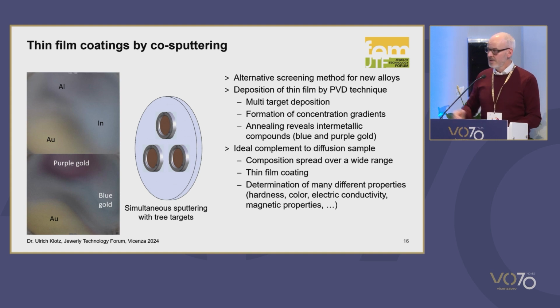So they are arranged in a triangle. And so they're sputtering material from different sides. So we get mixtures of alloying elements on this glass plate. And now we can anneal this glass plate, and we find the blue and the purple color forming. So the lower image is in the annealed condition. And this also helps us to screen interesting composition ranges. And now we can use different mixtures of sputtering targets to determine the resulting color. But of course, we can also measure other properties like the hardness, electric conductivity, and so on,